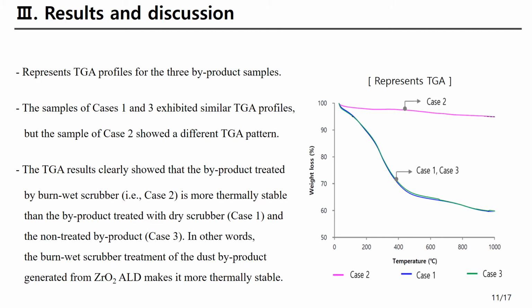This shows the TGA profile for the 3 byproduct samples. The samples of case 1 and 3 exhibited similar TGA profiles, but the sample of case 2 showed a different TGA pattern. The TGA result clearly shows that the byproduct treated by the burn-wet scrubber is more thermally stable than the byproduct treated with the dry scrubber and the non-treated byproduct. In other words, the burn-wet scrubber treatment of the dust byproduct generated from zirconium oxide ALD makes it more thermally stable.